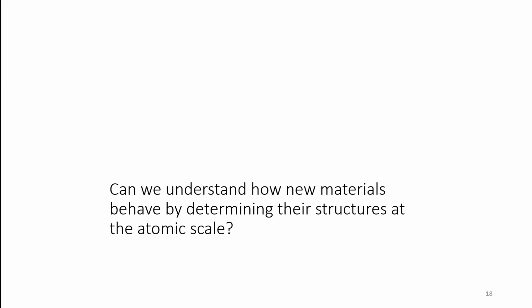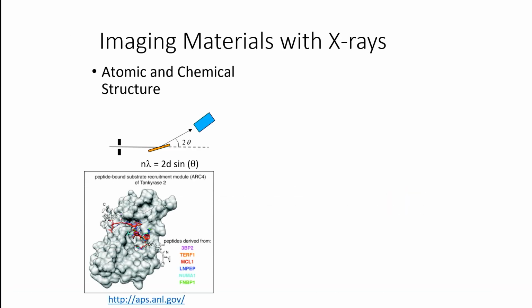All right, so let me skip that. And so once we have the materials, we can image them using the electron microscope. But my background is in using synchrotron X-rays in many different ways to understand these interfaces. One way you can use X-rays to understand the structure of a material is by X-ray diffraction. So you take your sample, you shine X-rays on it, the X-rays get diffracted onto a detector, and by measuring the intensity as a function of the angle, you can reconstruct that to go back to get the structure of your sample. This has been used for protein crystallography, and it's widely used in material science.